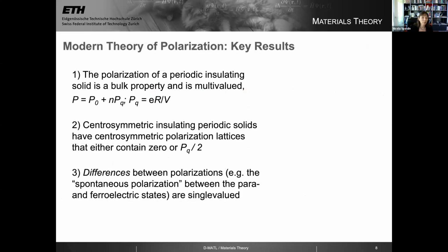Okay, so I'm adding that to my list of key results of the modern theory of polarization. Polarization is multi-valued. Centrosymmetric solids don't have to contain 0 in their list of possible values. And this is all okay because differences in polarization, for example the spontaneous polarization, which is the change in polarization between a paraelectric and a ferroelectric state, are single valued. And that is all that we can measure experimentally.